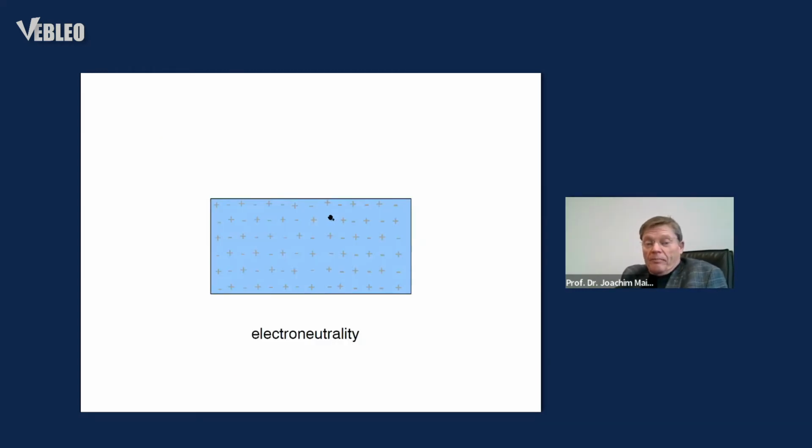So let's go a step back here and consider a bulk of a charge carrier containing system. That may in the simplest case be a liquid. Then you have positive and negative charge carriers, or in a solid, you have positive and negative defects. They are equal in concentration. So obviously, the one that is hardest to form will determine the equilibrium concentration. So it may be much, much lower. Maybe you would like to form more negative carriers, but you can't because you need the hardly formed positive carriers in the same way, in the same concentration.